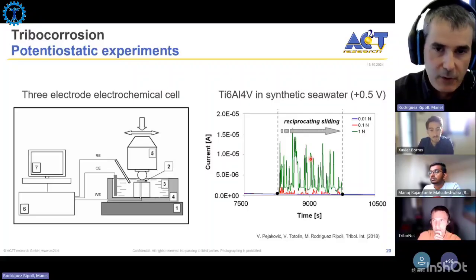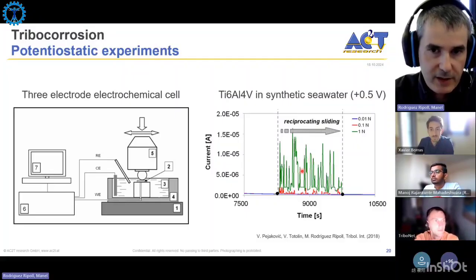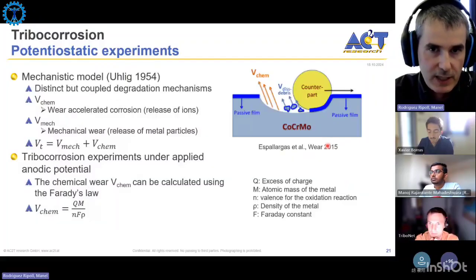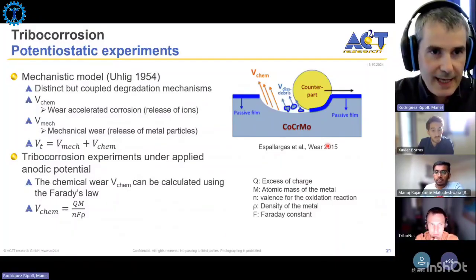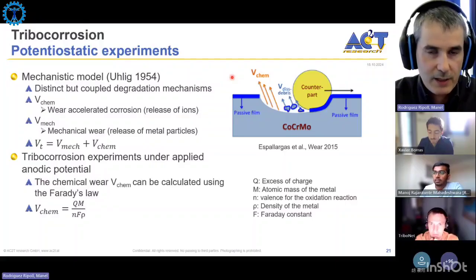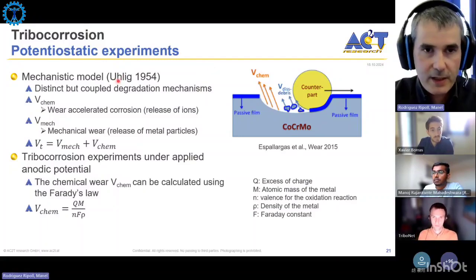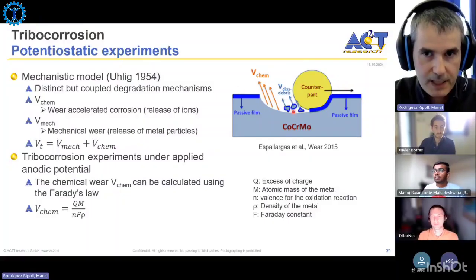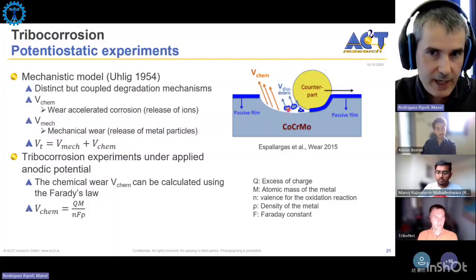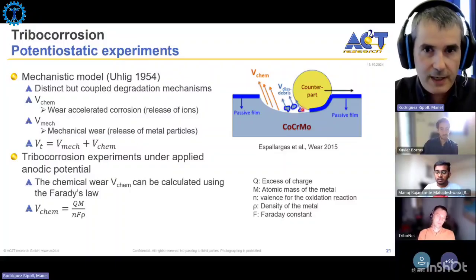And what is typically done to get quantitative data is to integrate this current, because when you make the integral of the current, you get the charge. And by knowing the charge, we will see that you can get the corrosion. And one of the most common models used to interpret this data obtained under potentiostatic conditions is the model proposed by Uhlig in 1954. And basically, it assumes that when you rub a passive metal, you destroy the passive layer, and the total removed wear volume by tribocorrosion has basically two contributions. One is due to mechanical wear, so the formation of wear debris, as we would have in other wear experiments, and the chemical wear here.